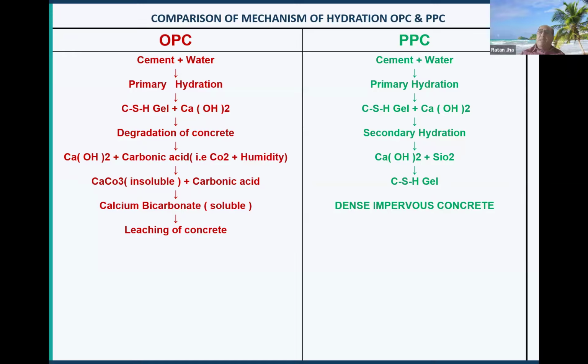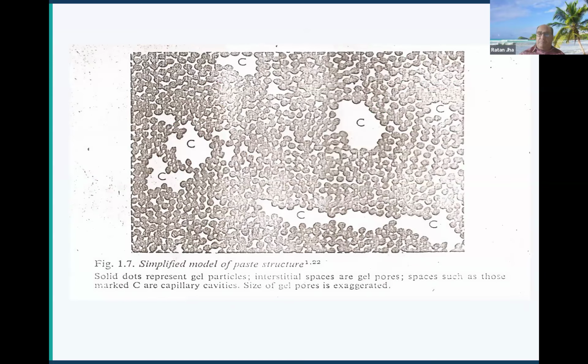or any concrete construction. Whereas in Portland Pozzolana cement or Portland slag cement, what happens? Since you have added fly ash, and in fly ash a sufficient amount of silica is present, that silica reacts with the calcium hydroxide in the presence of moisture and converts into additional CSH gel. That calcium silicate hydrate gel makes your concrete denser, and denser concrete has lesser permeability, and the leaching of concrete is almost nullified, making your concrete more durable with more service life.